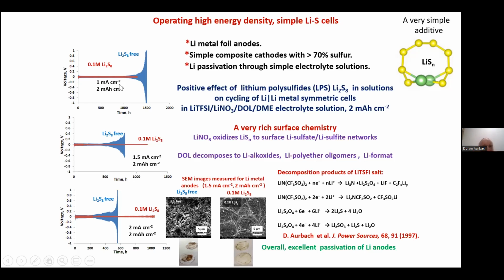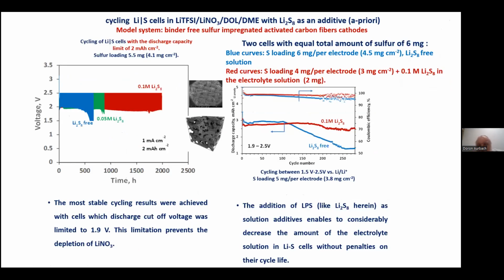Here you can see results of galvanostatic cycling of symmetric cells with the conventional electrolyte solution that is used in lithium-sulfur systems. Without our magic additive, we have a failure after some cycles, but with our magic additive, we can demonstrate very prolonged cycling of the symmetric cell. So now we can go to full cells, and indeed we demonstrate that compared to the reference, by using our magic additive, which affects the surface chemistry, and we know exactly what it does.